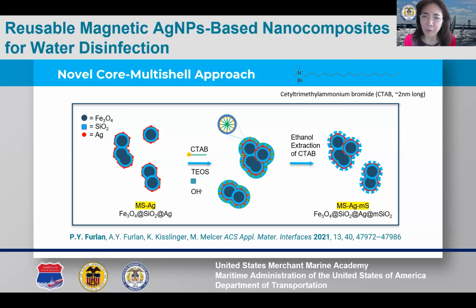In this process, we used CTAB, or cetyltrimethylammonium bromide, as the pore-forming template surfactant. In water, CTAB molecules, about 2 nanometers in length, self-assemble into micelles. These micelles, along with the silica oligomers, subsequently and cooperatively assembled onto the surface of MS-Ag particles. This assembly resulted in cylindrical CTAB micelles extending outward and surrounded by silica oligomers. Further condensation of silica oligomers formed silica walls between CTAB micellar channels. The later removal of CTAB molecules in ethanol produced the mesoporous silica outer shell.